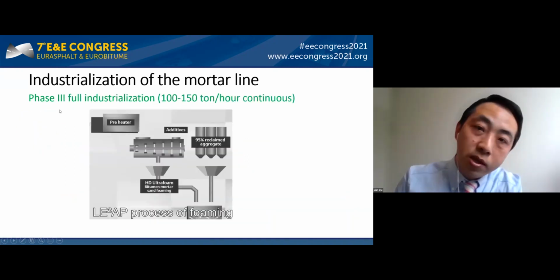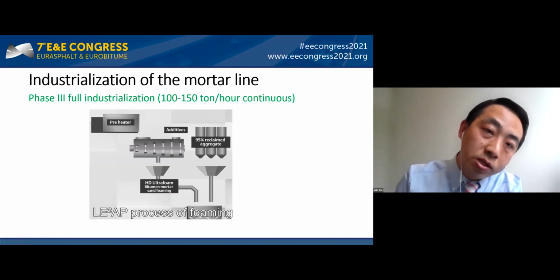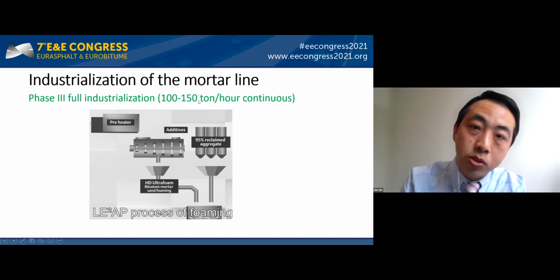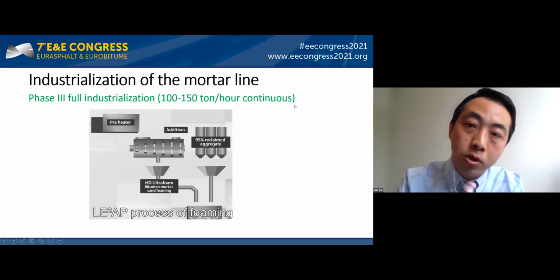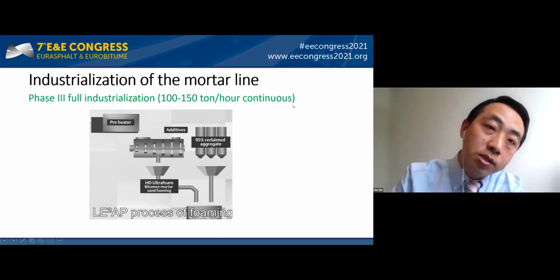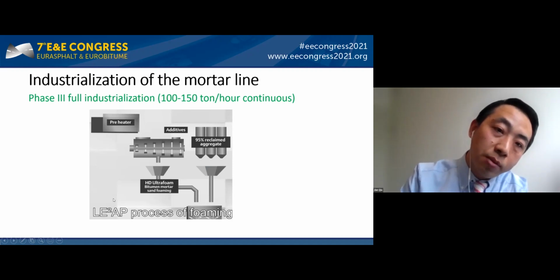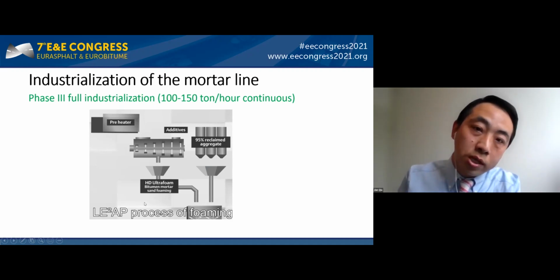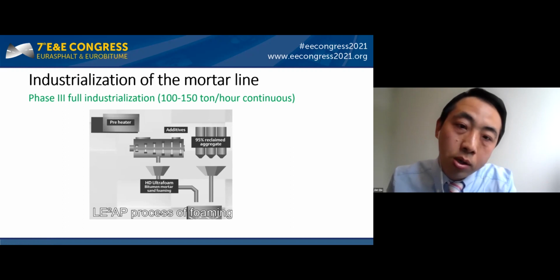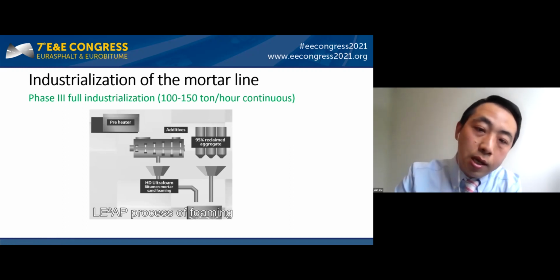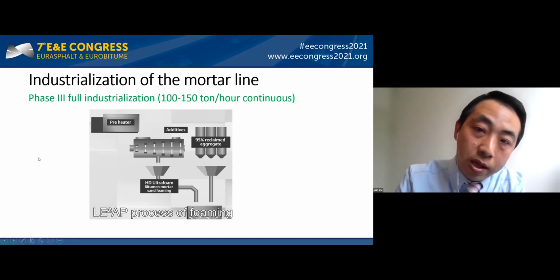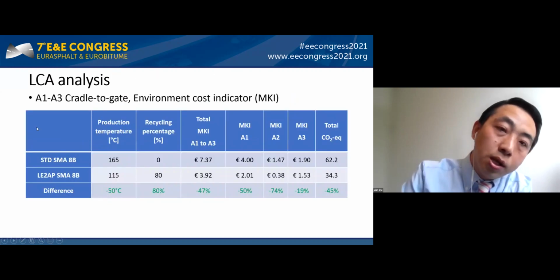The further step that we are now working on is to go for full industrialization. We want normal production to be adapted to 100 to 150 tons per hour of continuous production. Translated to the mortar part, that is about 20 to 30 tons per hour of continuous production. And with this, we are now working on it.